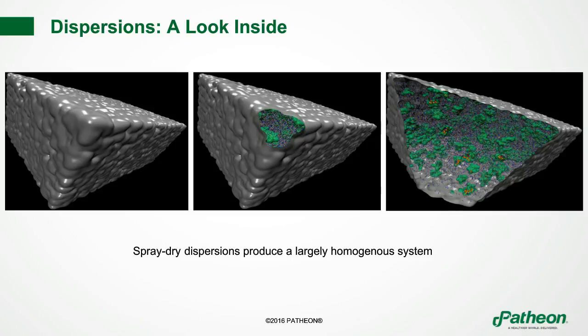And in fact, that's why sometimes you see differences in behavior, dissolution performance, between a spray-dry dispersion of the same materials and a hot melt extrusion of the same materials. We believe that might be the case. What might be going on there, I should say, is that you've actually got a non-homogeneous system in the hot melt extrusion, so it behaves differently. It's literally a different material than the homogeneous system of the spray-dry dispersion.